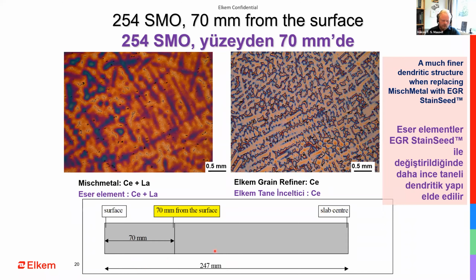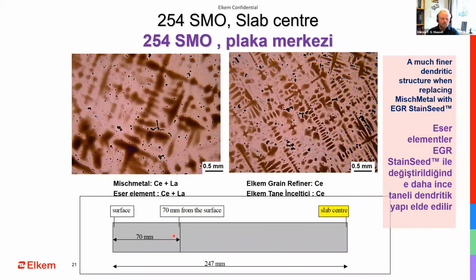So this is the test bar that I showed you earlier. So here we have, this is the surface of the ingot, and now we're looking 70 millimeters from the surface. If we then go into the center of the ingot, then we see it's an even more coarse structure when they used mish metal. And here you can see it's much finer with the EGR Stainseed.